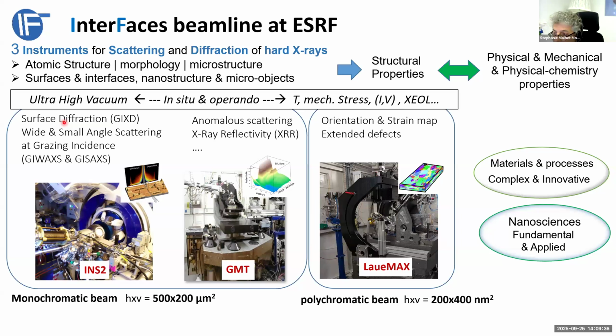We are able to do some wide and small angle scattering, and since we want to be sensitive to the surface, it's better to enhance the signal coming from the interface and the surface, so we need to illuminate the sample with grazing incidence. This is what I'm calling grazing incidence wide angle X-ray scattering, or grazing incidence small angle X-ray scattering. There is also the possibility to change the energy of the monochromatic beam in order to enhance the signal coming from a specific element in your materials. And also what we are doing a lot is X-ray reflectivity.